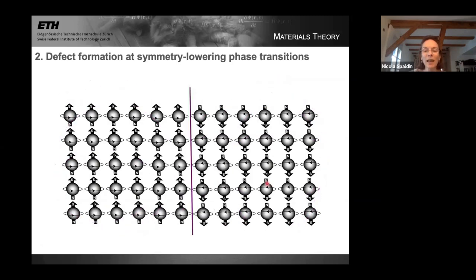And at the intersection between these two regions, I have what we know as a domain wall in the case of ferromagnets. This is a planar defect in a uniaxial ferromagnet. So this is a defect. The lattice is not beautiful and periodic anymore. It's upset here. There's a discontinuity in the orientation of the spin. And it's higher energy than the surroundings, right? The low energy state is for the spins to be lined up parallel. And so this magnetic moment here is in a higher energy state because its neighbor doesn't have the right orientation. So associated with symmetry lowering phase transitions then is the formation of defects.